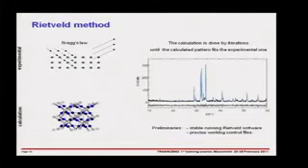You start off with simple mixtures. You make sure things are working for simple mixtures, then you extend to more and more complicated mixtures, and these are what are called your control files. So the accuracy of your Rietveld analysis depends very, very much on your control files, which are built up over time and experience of analyzing different mixtures. So that's just what I say here.